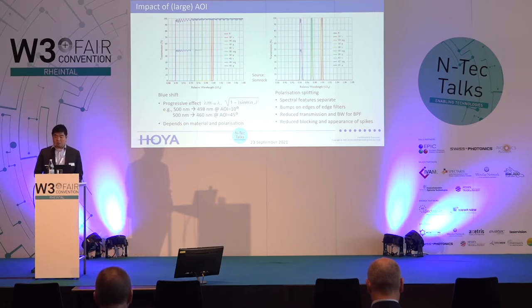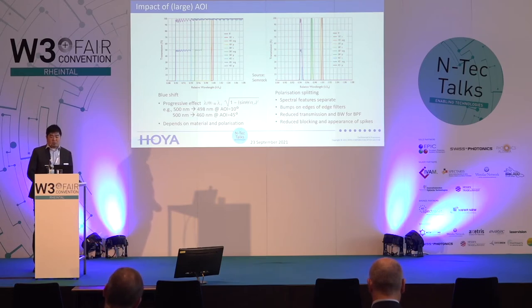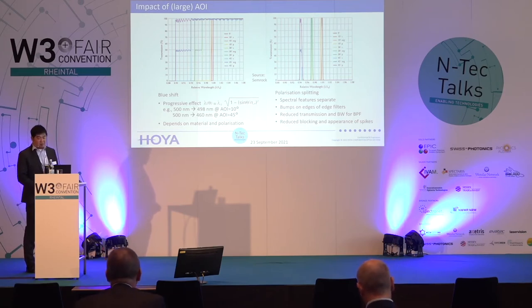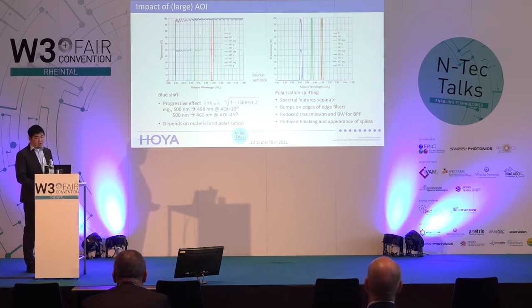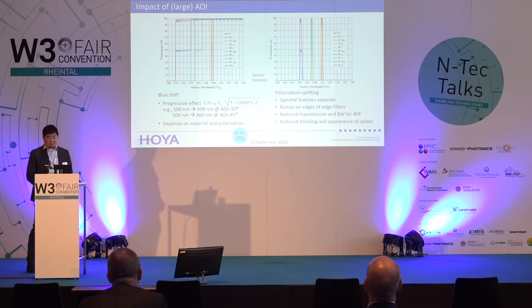Thin film interference filters have a natural property, which is sensitivity to angle of incidence. The spectral properties will shift towards shorter wavelengths because the path length of the optical rays changes in the filter. So you can see on the left-hand side plot 0, 10, 30, and 45 degrees angle of incidence. And from the formula below, you can see the blue shift, which rapidly becomes severe beyond 10 degrees. For example, at 10 degrees, you only have a 2 nanometer shift, but at 45 degrees, you already have a 40 nanometer shift.